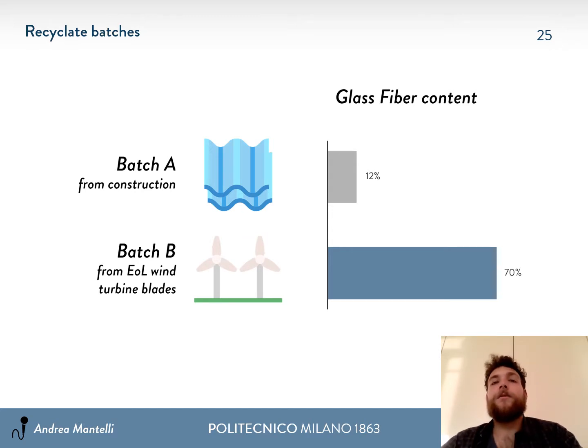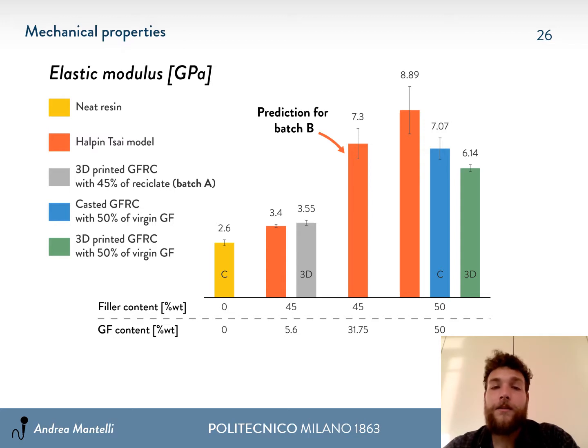All the tests have been made with recyclate batch A from the construction industry, and this recyclate is very poor in glass fiber content. But now, considering the new recyclate that we received from end-of-life wind turbine blades, the content of glass is very high, and we have been able to measure the recycled glass fiber length and radius, and in this way we can calculate the elastic modulus with the Halpin model. Here you can see that even though the filler content is 45%, with batch B we can reach a higher content of glass fiber, and so the predicted elastic modulus is higher and comparable with the mechanical properties of a composite made with virgin glass fibers.